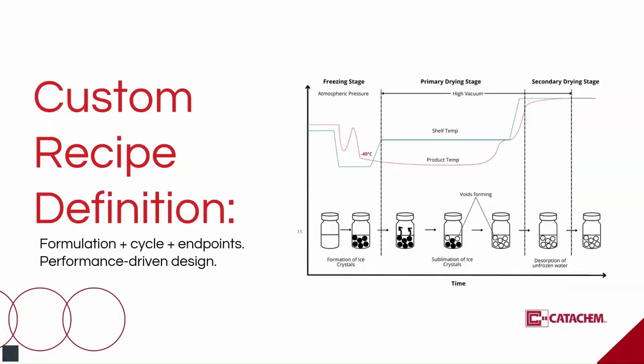So what makes a custom recipe truly custom? A freeze-dry recipe is not a list of shelf temperatures. It is an engineered relationship between formulation thermal limits, ice morphology and pore structure, product temperature behavior under load, chamber pressure control for stable mass transfer, and endpoints that correlate with performance, moisture, reconstitution, potency, and stability. Two formulations with similar concentrations can require very different cycles because excipients, buffer salts, protein structure, and fill geometry change the collapse limit and the resistance to sublimation.